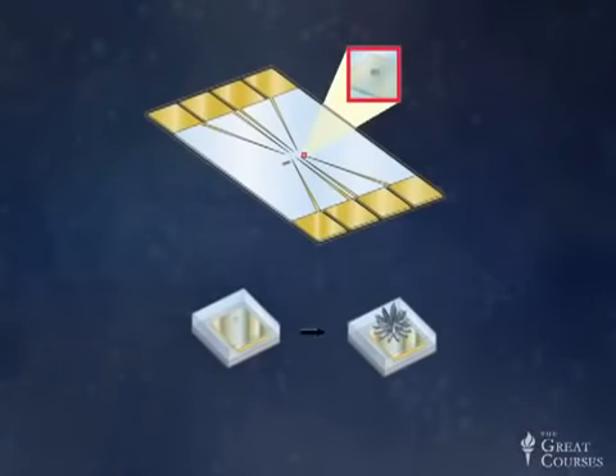We take our chips, we put them in a bath of metal salt, we apply a potential, and that causes metal to electroplate onto the chip. And this is what gives us our nanostructuring. As the metal plates onto the chip, it forms tiny nanostructures that are actually quite easy to manipulate. So, for example, if we use 3 different conditions for electroplating, we can get 3 different levels of nanostructuring.